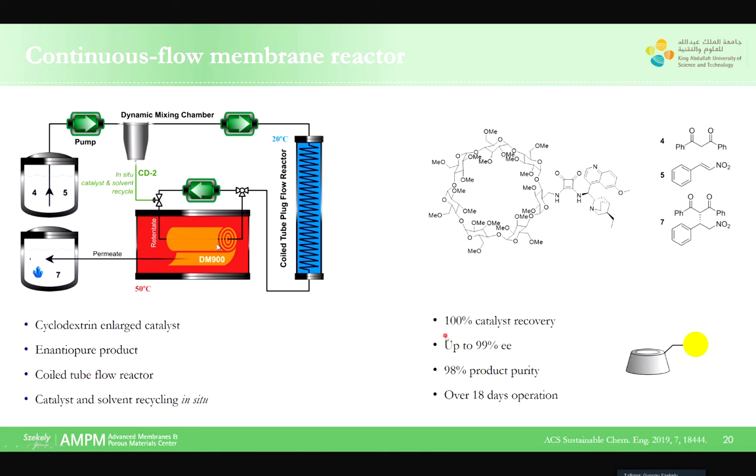And in numbers, we achieved virtually 100% catalyst recovery, high enantiomeric excess again, high product purity, and we performed this continuous operation over 18 days and obtained stable performance. So again, if you're interested in the details of this work, then I recommend our publication on this research.